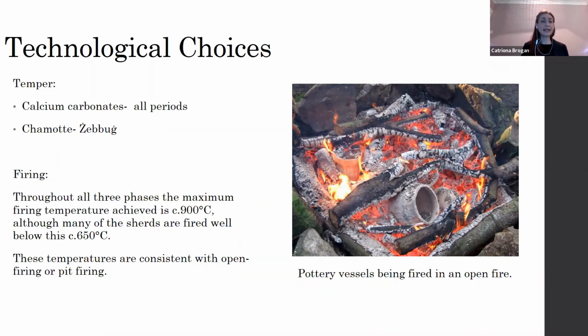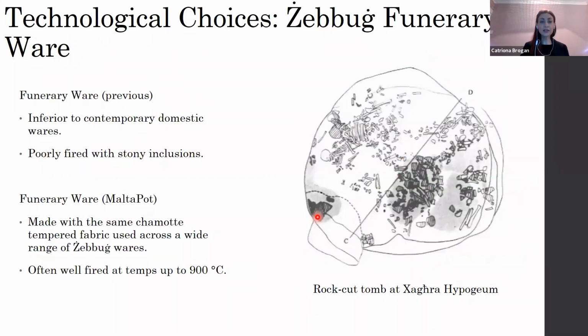And then if we briefly look at the firing, we can tell that the maximum temperature achieved for any of these pots was about 900 degrees. So this suggests that they were probably being fired in an open fire such as this, or in a pit fire, because really you need something like a kiln to achieve higher temperatures than that. So this would explain as well if they were just being fired in these pits or bonfires where we have no archaeological evidence for the firing process. We don't have the kilns like we would have later.